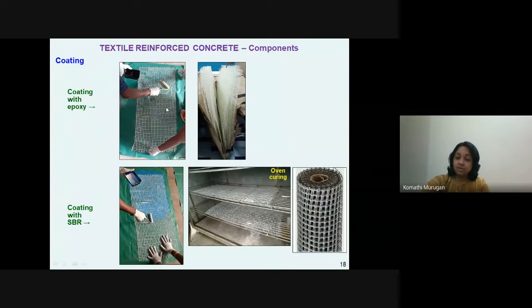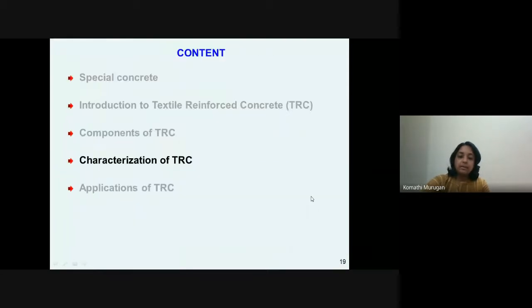Like it at least consumes a day. But what happens when we coat it with the styrene butadiene rubber or SBR? We have a specific SBR which is developed for coating the textiles. We have to coat the textile panels with SBR, keep it in an oven at a specific temperature and for a specified duration of say 30 minutes. In 30 minutes, what we get is something like this, which is a flexible textile. The SBR coating on a textile results in flexible textiles.